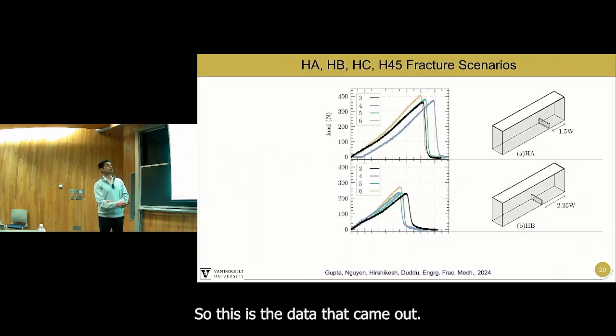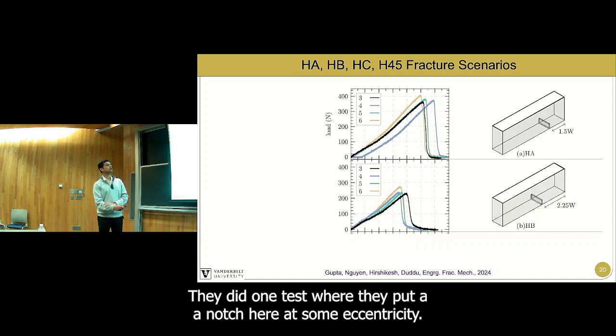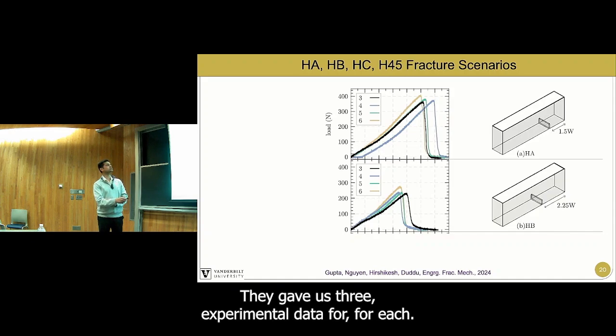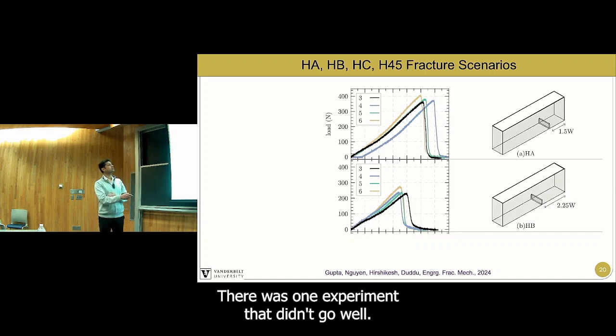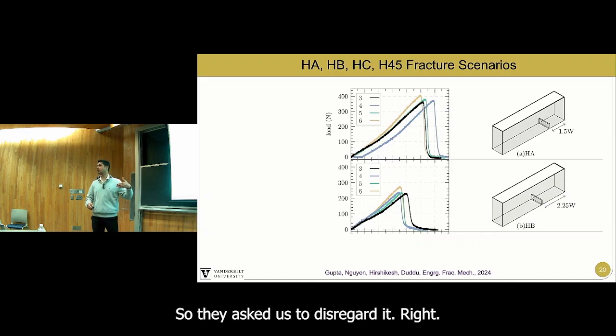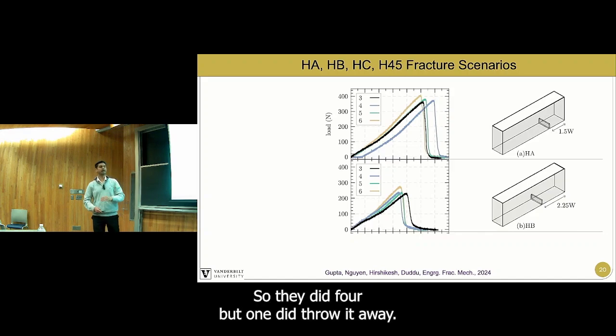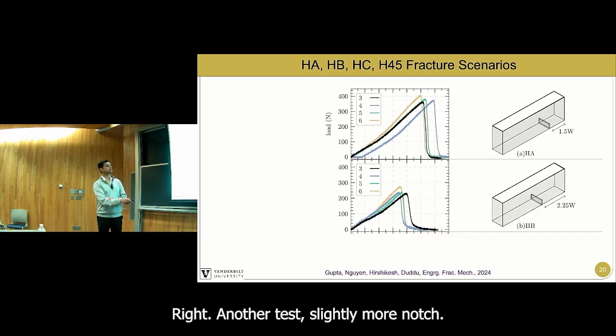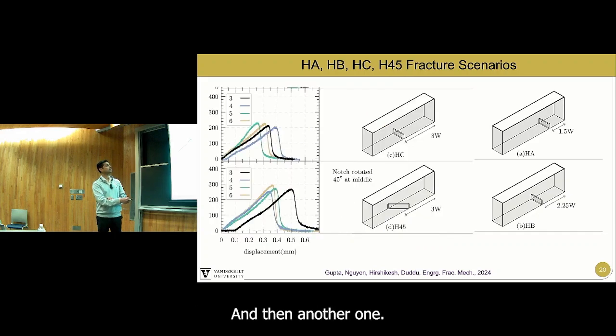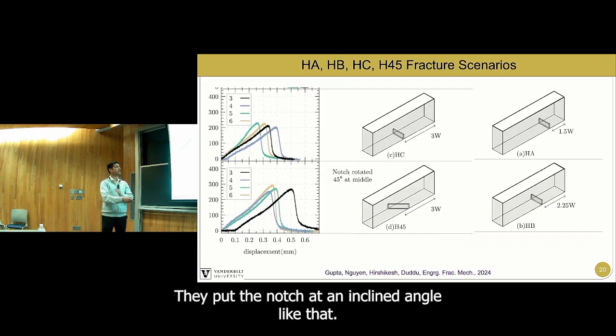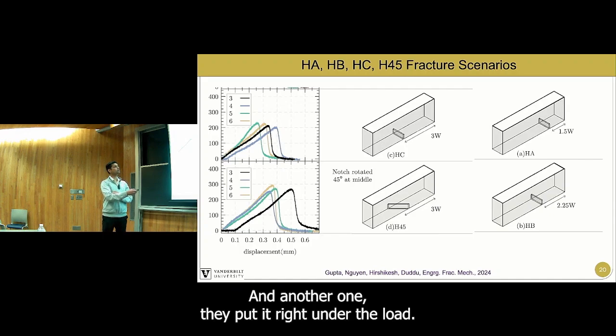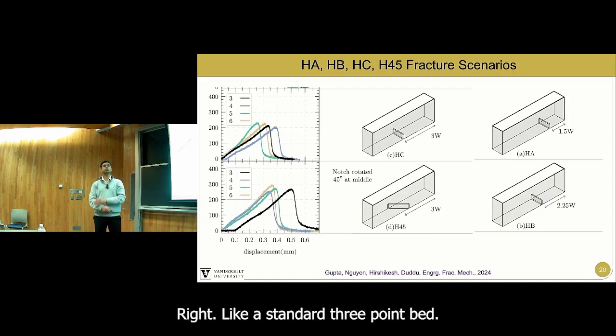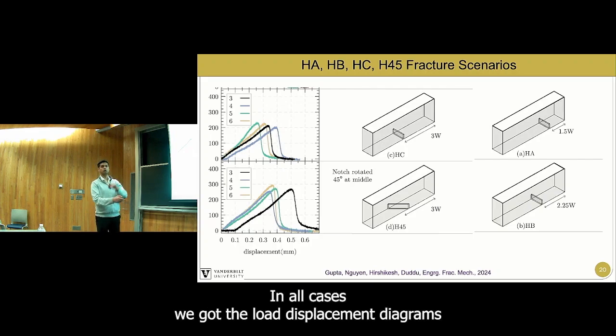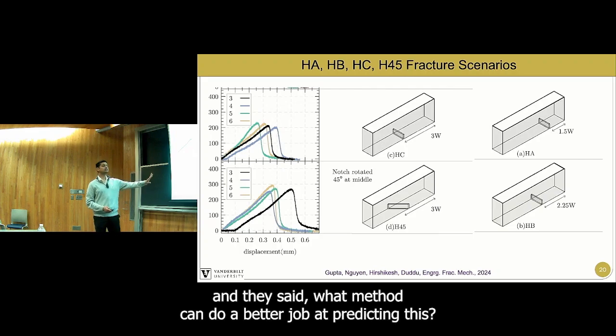So this is the data that came out. They did one test where they put a notch here at some eccentricity. They gave us 3 experimental data for each. There was one experiment that didn't go well, so they asked us to disregard it, right? So they did 4, but 1 they threw away. Same thing with another test, a slightly moved notch, and then another one, where they put the notch at an inclined angle like that, and another one, where they put it right under the load, like a standard 3-point bend experiment. In all cases, we got the load displacement diagrams. And they said, what method can do a better job at predicting this?